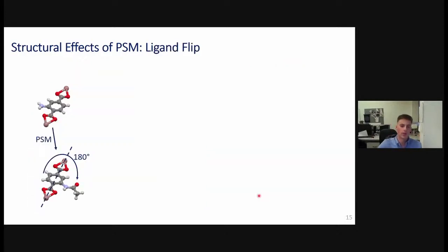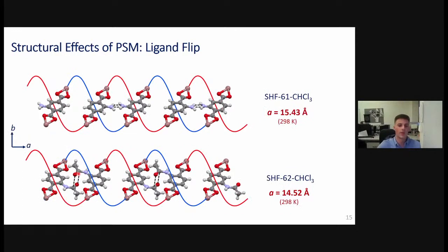And the reason that those two positions switch is due to the fact that the post-synthetic modification drives this organic linker, the 2-amino terephthalic linker, to rotate 180 degrees. And it's this post-synthetic ligand flip that facilitates these new interactions between the two networks. And those interactions are optimized by a contraction of the A-axis. So the A-axis is shown along here. And you can essentially think of this as a spring which is compressing to optimize the geometry of those new interactions between the two networks.